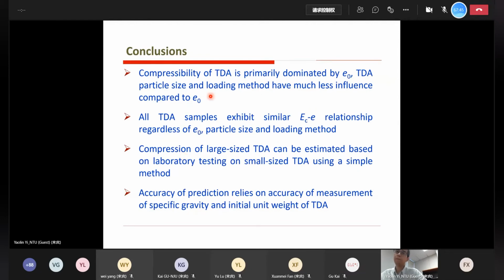The first one: the compressibility of TDA is primarily dominated by the initial void ratio, and the particle size and loading method actually have much less influence compared to the void ratio. This is because this material is quite different from soil, because it's a very perfectly elastic material. I mean the particle, because it's just rubber, so it's easy to deform. So, for example, the clogging and interlock of the particles is actually quite small.